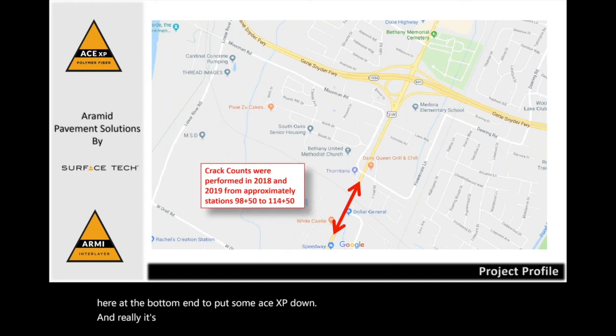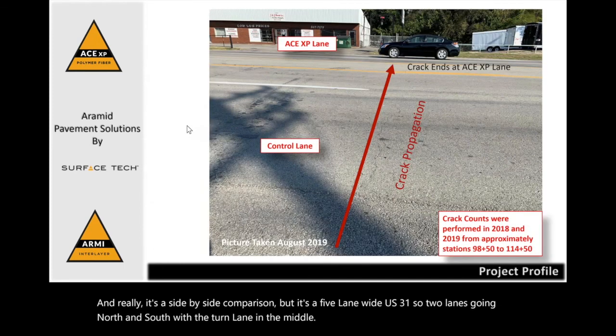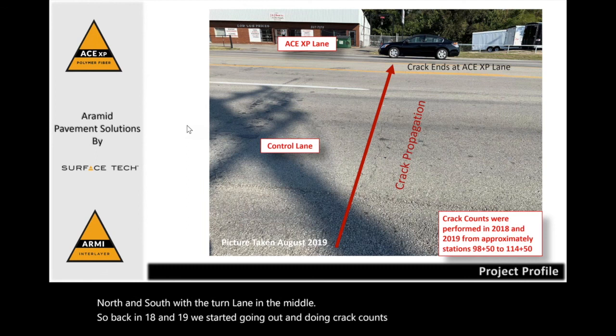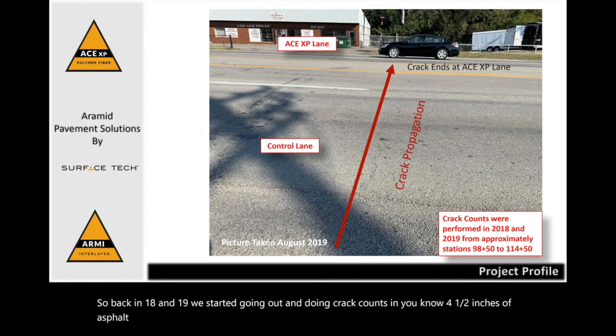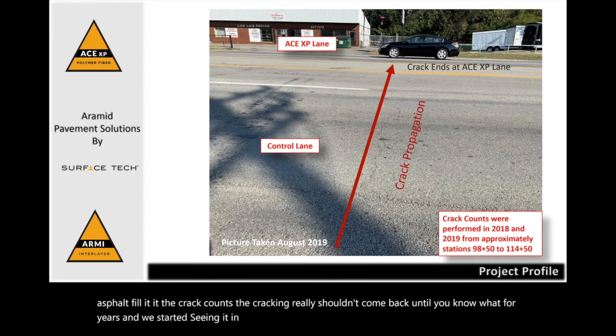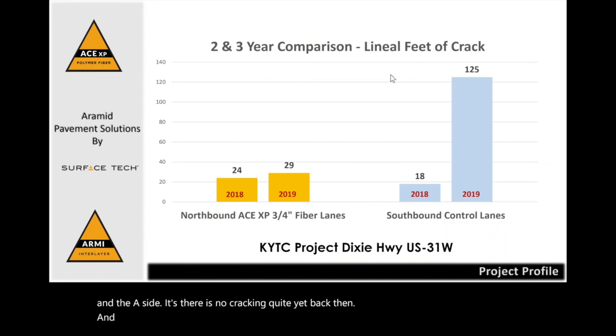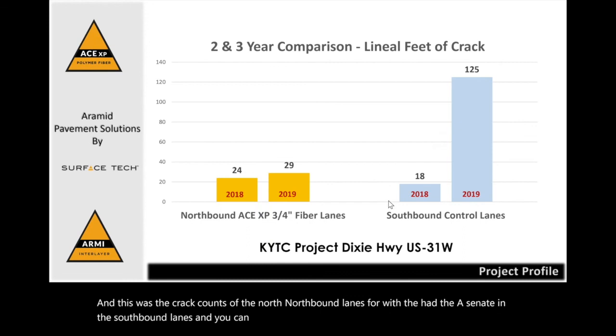And really it's a side-by-side comparison, but it's a 5-lane wide US 31, so two lanes going north and south with a turn lane in the middle. So back in 18 and 19, we started going out and doing crack counts. With 4.5 inches of asphalt fill, the cracking really shouldn't have come back until 4 years. That's right. And we started seeing it in 19, so it was kind of right on cue. And this is the control side and the ACE side. There is no cracking quite yet back then. And this was the crack count of the northbound lanes with the ACE center and the southbound lanes. And you can see the cracking starting to really ramp up on the control lane.